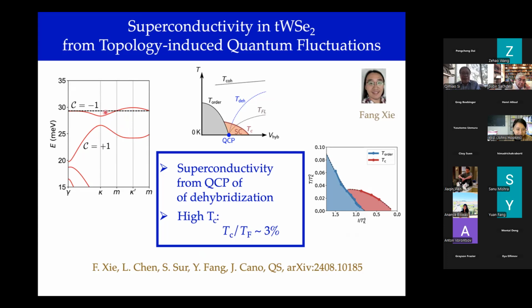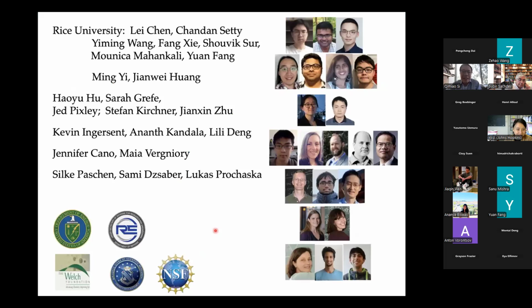Here, the bands are much simpler, and there's a clear case to be made that electronic order is natural because of, in this case, half filling, but at least partial filling of a flat band. And yet, there's not only from this perspective a natural tendency for topologically ordered, typically insulating phases, but also for this kind of quantum fluctuation regime that drives superconductivity. So it's almost like you have a big parameter space in which some portions of parameter space realize something like fractional Chern insulators. To really realize that is hard work theoretically as well. But conceptually, in the other region of it, one has amplified quantum fluctuations and realizes nominally high TC superconductivity. So that's all that I want to say.